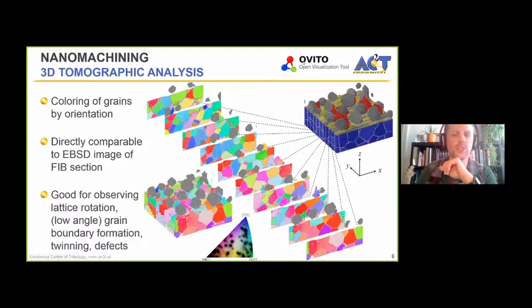visualization tool, which is still open source, named Ovito. That can do polyhedral template matching to get the orientations of the grains. It can do dislocation analysis. It's a very powerful tool. And by doing that and then visualizing, I can actually make sections that look very much like an EBSD picture that a material scientist might get from cutting a FIB lamella, putting it into the SEM and waiting for a couple of hours until they get a high resolution EBSD image.